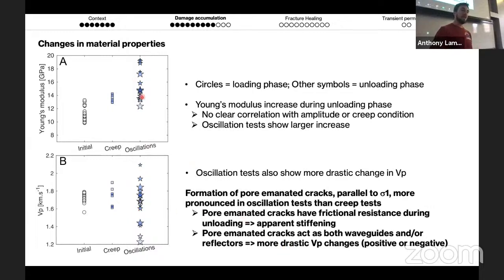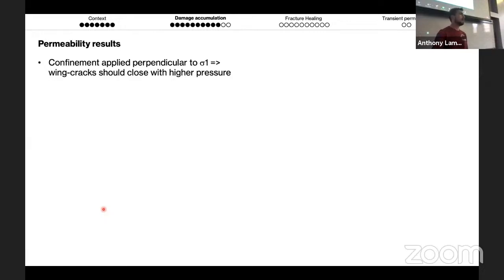So what that means altogether is that the bigger changes in both of these variables tell me that there is more damage created during the oscillation test than during the creep test. And if you're not convinced yet, then the permeability is basically the final nail in the coffin here. In our rig, the confinement is applied perpendicular to those cracks I should have formed. So the more pressure I put around them, the more crack closure I should have, and therefore the bigger permeability reduction I should have. Okay, so that's what it should see. So the more damage, the faster the permeability should change with increasing pressure.